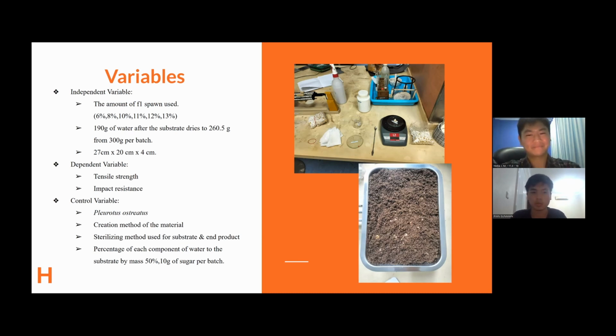We did this because we wanted to do 300 grams substrate, then added 190 grams of water. But if the substrate dries, we need to compensate for that. Also, the mold is 27 by 20 by 4. The dependent variable is the tensile strength, but mainly the impact resistance, because we tested that. The control variable is the type of mushroom we use, Pleurotus ostreatus.